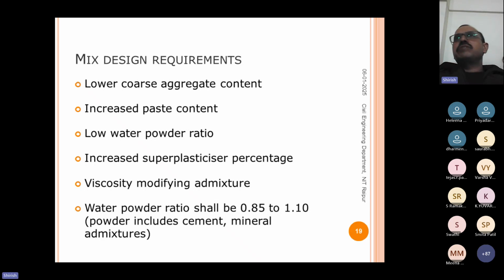So then what is this viscosity modifying admixture? They are very fine particles of polymer which are dissolved into water, and this material is added into the concrete. What it does is, it does not allow the water to remain free in the concrete. These finer particles hold the water within the concrete and do not allow it to bleed. Now, whenever water added is higher, as I just said, there is a tendency of water to bleed. So the viscosity modifying admixture, with very fine particles, will not permit the water to flow out of the concrete, meaning they will restrict the bleeding. And then when water remains within the concrete, it will allow all the materials to flow together.